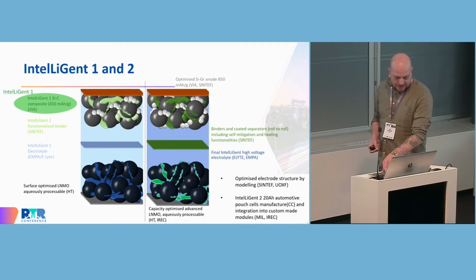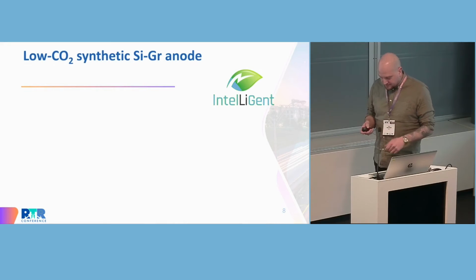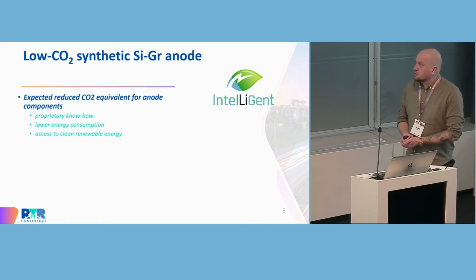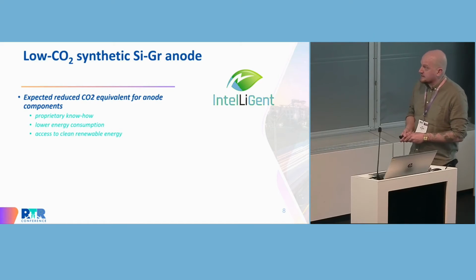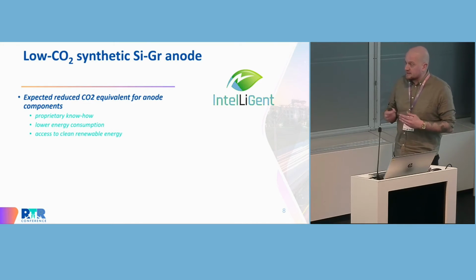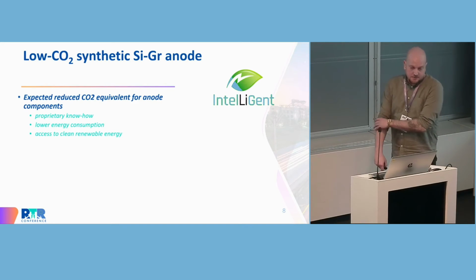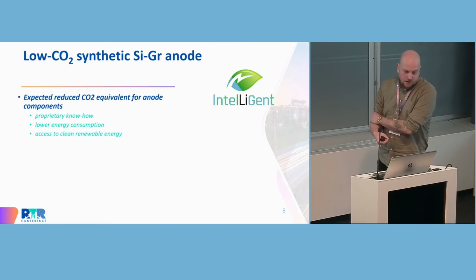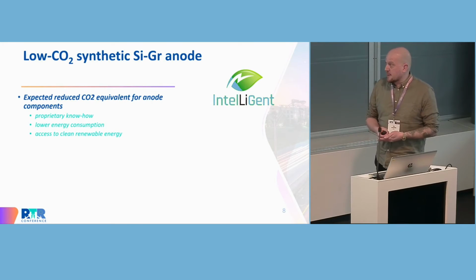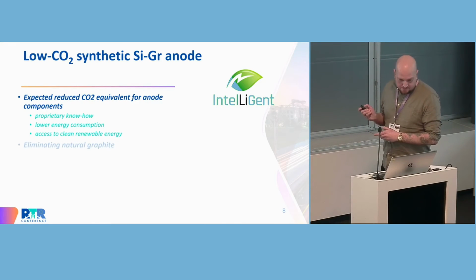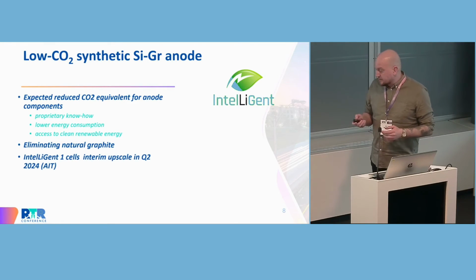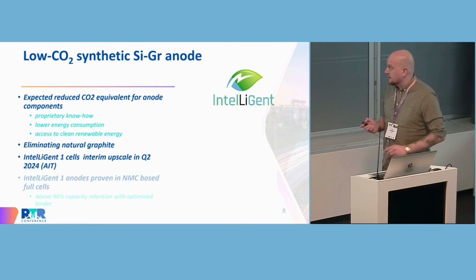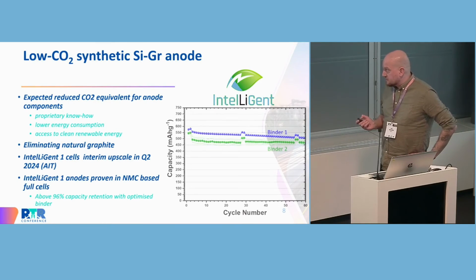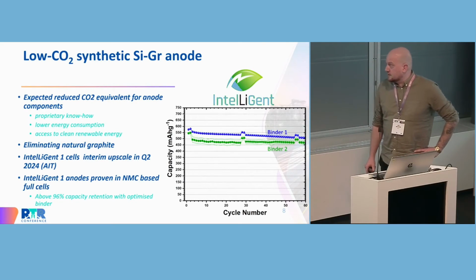If we move further down the anode side of things, my favorite topic because it's so difficult, we're talking here about a low CO2 equivalent synthetic silicon graphite. So we expect to reduce the CO2 equivalent for these anode components in comparison to state-of-the-art materials by our partners' proprietary know-how, and also their process with a lower energy consumption. And the process is placed in Norway and based on clean renewable hydropower. We of course then eliminate natural graphite, and the first interim, I already said that is supposed to happen next quarter.